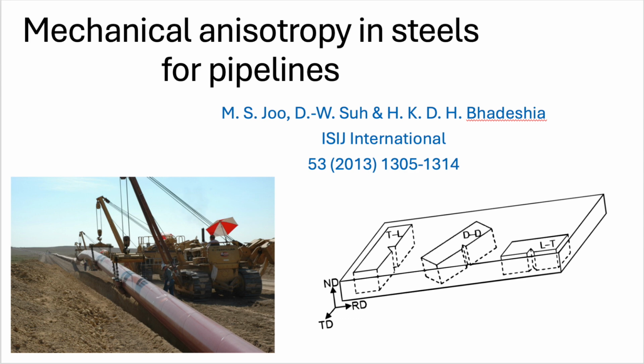Precisely. Then, just like with the inclusions, when you hot roll this slab, those chemically enriched regions get squashed and smeared out into long bands parallel to the rolling direction. And manganese is particularly bad for this. It is, especially if the cooling after rolling is relatively slow. The manganese-rich bands tend to transform into pearlite, a harder layered microstructure, while the surrounding areas become softer ferrite. This creates distinct ferrite-pearlite bands. So you get layers of harder and softer material running through the steel.